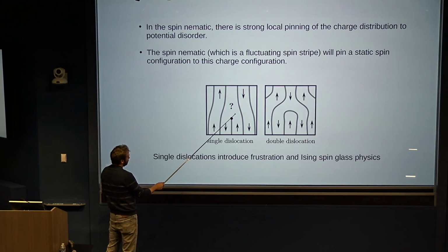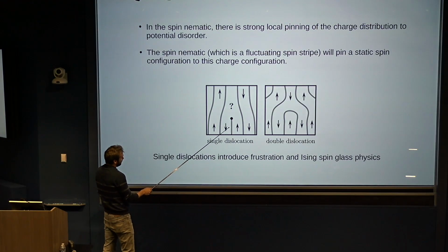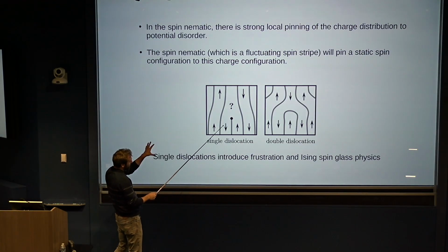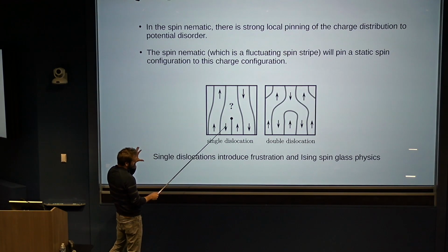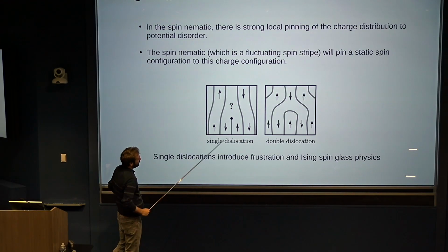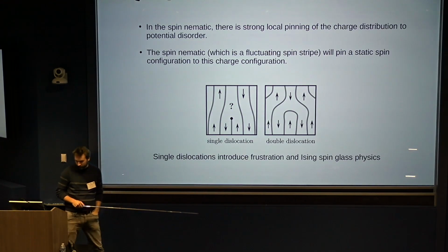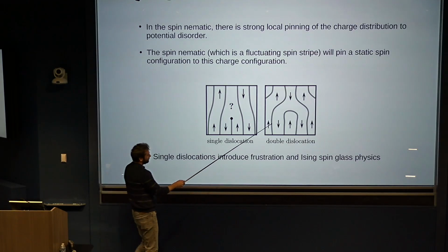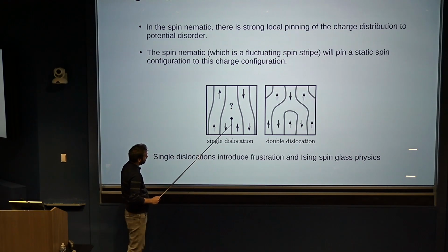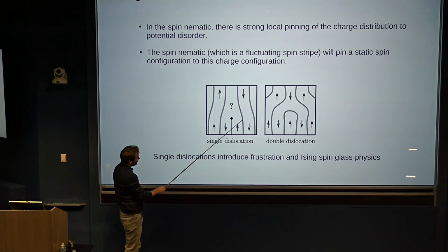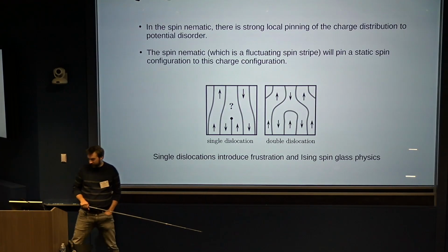They don't really know what to do, because when they cross such a line, they should change their direction. But you can go from here to here either by not crossing such a line or by crossing such a line. So there's an ambiguity on how you should pin the spin order to this charge order. Of course, if you have a double dislocation, then there's no problem. It's really only the single dislocations which introduce frustration into the problem.